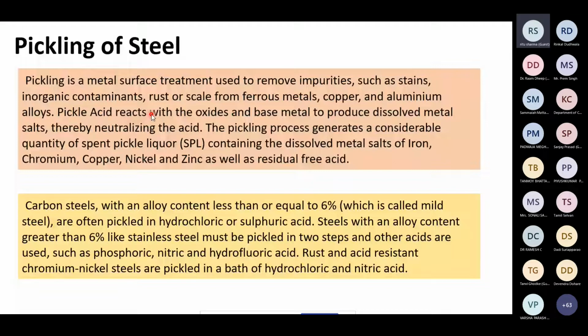Pickling is a metal surface treatment used to remove impurities such as stains, inorganic contaminants, rust or scale from ferrous metals, copper and aluminum alloys, etc. Pickle acid reacts with the oxides and base metal to produce dissolved metal salts, thereby neutralizing the acid. So metal salts are generated, meaning one of the solid materials is getting generated. The pickling process generates a considerable quantity of spent pickle liquor, SPL, containing the dissolved metal salts of iron, chromium, copper, nickel, zinc, as well as the residual free acid.